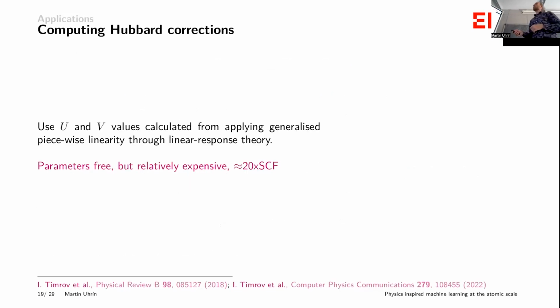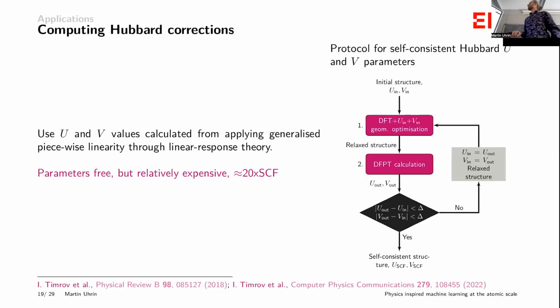So these things, the U and V values that correct for this, they can be calculated fully analytically, no approximations needed, but it's very, very expensive. So it will typically cost you around 20 times a normal calculation to calculate those values to then plug back into your system. But the story actually gets even worse because you have to take your atomic structure, make a guess for the U and V, allow it to relax, recalculate your U and V, and then check, hold on a minute, have they changed much, the U and Vs? If the answer is yes, then you need to actually go back around this loop and recalculate, re-relax your atoms, and pay this cost each time you go around this loop.